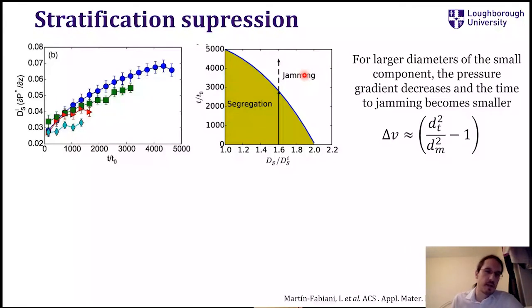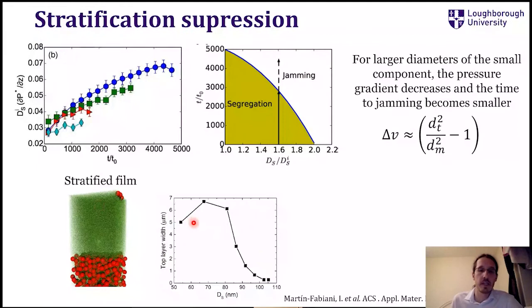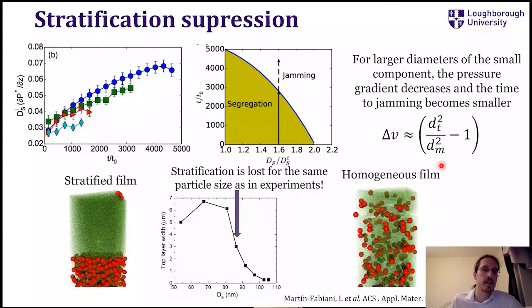So my colleague Andrea, again, did some modeling, and he had a look at the film when it was stratified, with the small particles on the top, and then he was changing the size of the small particles, increasing it, and measuring the width of this stratified layer. And you can see that at some point this width is reduced to almost zero when you increase this, which is the same as increasing the pH, and then you end up with a homogeneous film. And he saw that the stratification is lost at exactly the same particle size as in the experiments that I had done. So this was a very good way of correlating. But this is another tool: we have this stratification, but we can switch it on and off as we think we need it.